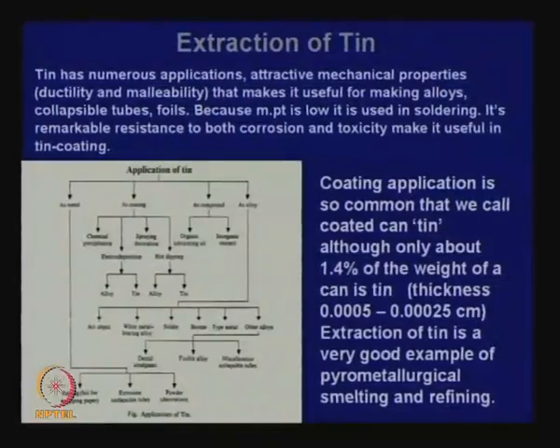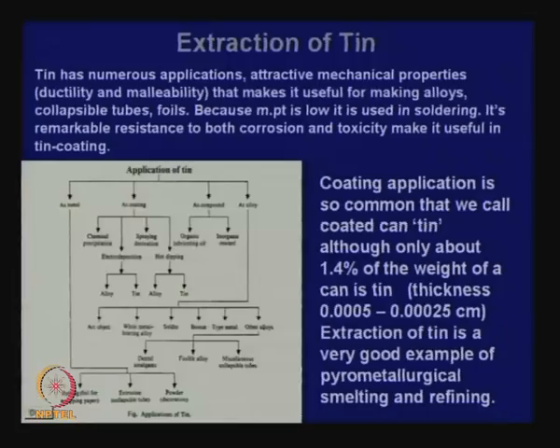Interestingly, the amount of tin on a coated can is actually very small. Only about 1.4% of the weight of the can is tin, and its thickness is as small as 0.0005 to 0.00025. So, you imagine how thin that tin coating is, and it is extremely effective. It is impervious, it makes the can inside at least corrosion resistant, and it prevents degeneration of the beverage or food material contained inside.